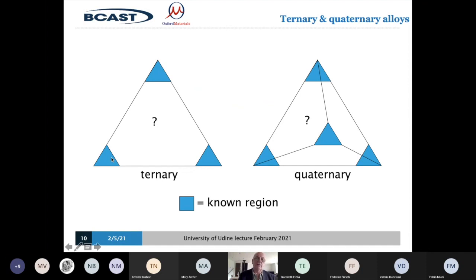All of our materials and alloys, because of this normal alloying strategy, which was never enunciated, but just used, all of our alloys tend to be at the corners of a diagram like this. All our three-component systems are usually at the corners and not right in the middle, the near equiatomic compositions. And if we go to four-component systems with a quaternary system, as depicted in a tetrahedron, it's even less likely that we know anything in the middle of this, what's called a phase diagram. If we go to 5 and 6 components, we know almost nothing about them. Well, we've begun to learn it just recently.